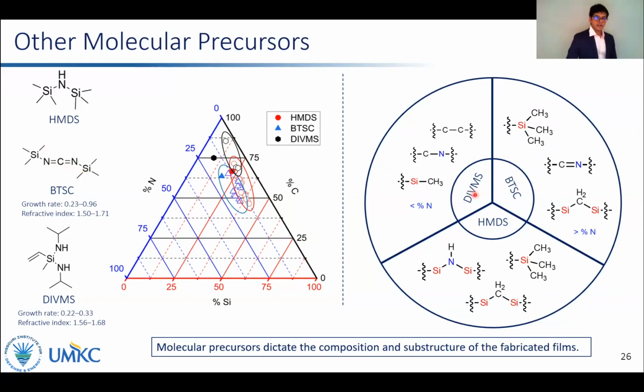DIVMS precursor derived films exhibited simple structural moieties such as terminal methyl, CN, and CC bonds. Interestingly, it incorporated a lesser amount of nitrogen in the films compared to HMDS films, even though the precursor had two nitrogens in it. So overall, molecular precursors dictate the composition and substructure of these fabricated thin films, supporting our initial strategy of choosing structurally different molecular precursors.